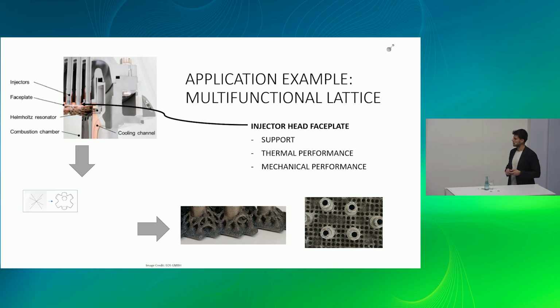In a hot firing test, it actually turned out that there's a heat buildup due to that support. So it was a massive structure, and the heat was concentrating in these cones. The faceplate was getting too hot, with the consequence that it would actually melt if we would increase the temperature even more. So what we did is we transferred these cone structures into a lattice structure. One of our propulsion engineers actually wrote a script in CAD, so an algorithm that transfers these cones into a lattice structure. You can see that applied here.